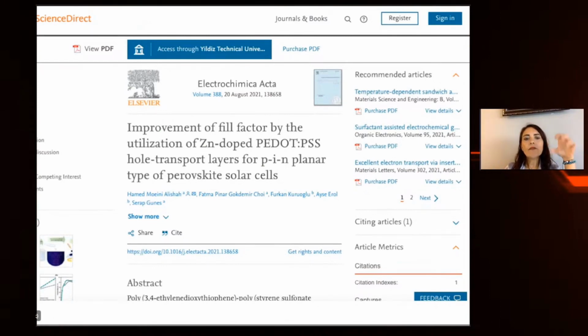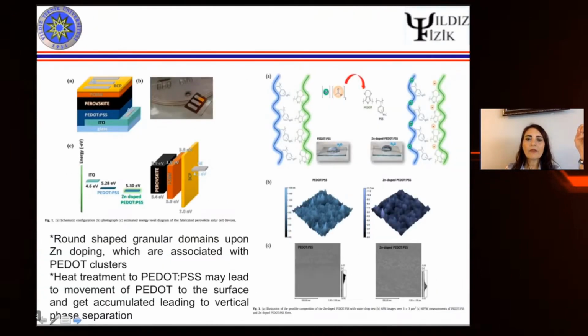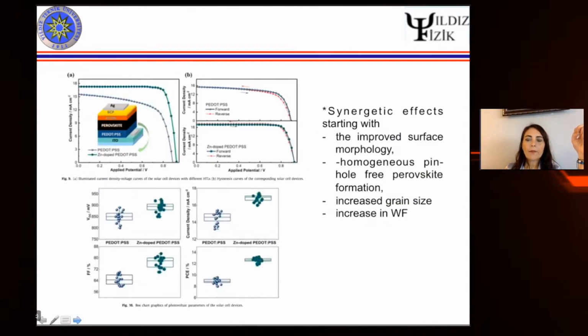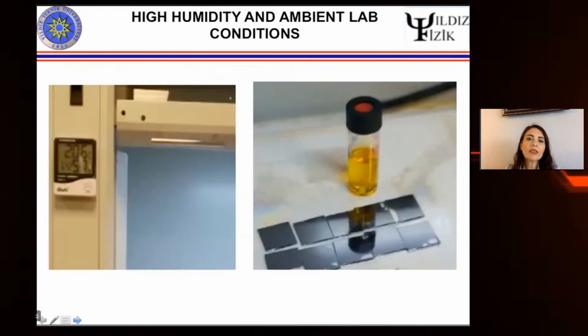Later on, we had learned from the previous studies that when nickel oxide is doped, the solar cell performance is improved. And we went back to our old friend PEDOT:PSS in this PIN structure, and we were asking this scientific question: is it possible to apply a kind of doping to the PEDOT:PSS, and would the efficiencies improve or not? We were trying to understand that, and as a result of this study, by zinc doping of the PEDOT:PSS and by heat treatment of the PEDOT:PSS layer, we concluded that the synergetic effect, starting with the improved surface morphology, homogeneous pinhole-free perovskite formation, increased grain size and increase in work function, actually led to an improvement in the power conversion efficiency.